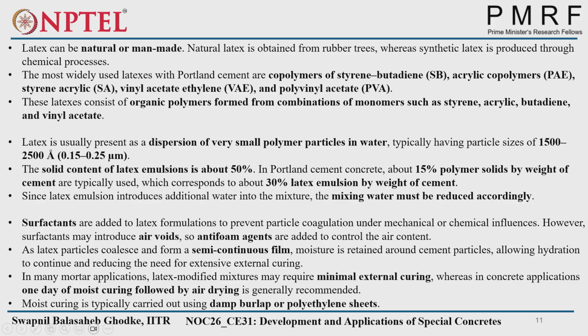So that's why external curing will be minimal in the case of latex-modified concrete. We can reduce the initial water, and we can reduce the external curing also. In concrete applications, 1 day of moist curing followed by air drying is generally recommended. Since curing is reduced, 1 day of moist curing and after that dry curing is fine for this type of concrete. Moist curing is typically carried out using damp burlap or polyethylene sheets.